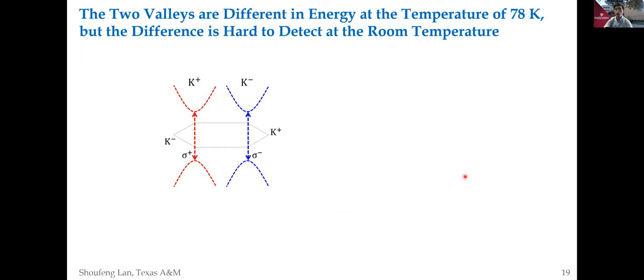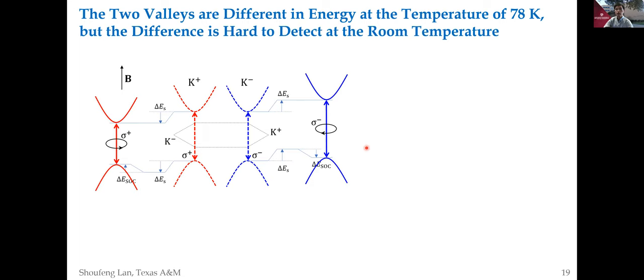And second, let's look at the magneto-optical effect by placing a monolayer WS2 on top of a ferromagnetic substrate such as TIG. The TIG can provide a magnetic moment. First, the magnetic moment will interact with the spin, which leads to the interband transition shift, delta E_S. The delta E_S has the same magnitude but a different shifting direction for the two valleys. And because of spin-orbit coupling, it will also induce an interband transition, this time mainly focusing on the valence band. So the shifted band structure will have different energy levels as well. When we shine a light that has the same energy, the population of the two valleys will also be slightly different due to the Fermi distribution.